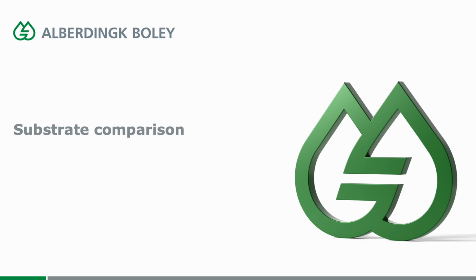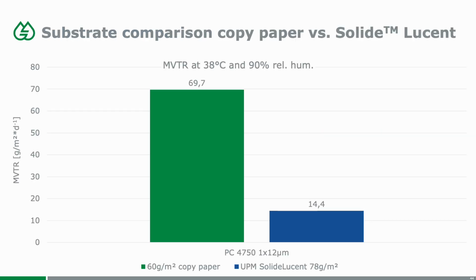As we have been looking at the results on the Solide Lucent paper now, let's have a look at a substrate comparison. So if we compare the copy paper that you've seen before in all the testing versus the Solide Lucent paper, and we just look at the MVTR at tropical conditions, you see that on the copy paper we are ranging at roughly 70 grams per square meter per day, but changing to the proper substrate we are able to go down to 14, which as I said before stresses the importance of the right paper for the individual application.